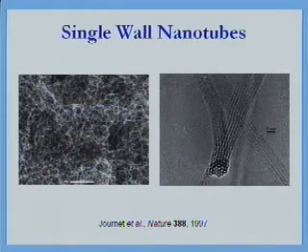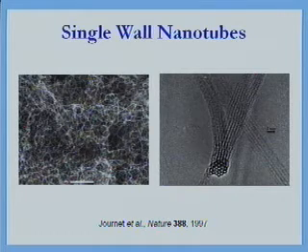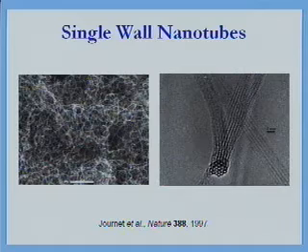Once you wash it out with water, you get these nanotubes into liquid, and on the right is a representative image of one nanotube bundle. You can see that in one bundle there are about 5 to 10 different nanotubes aligned with each other. This alignment is due to the interparticle attraction between the two, or the capillary interaction between the two rods.